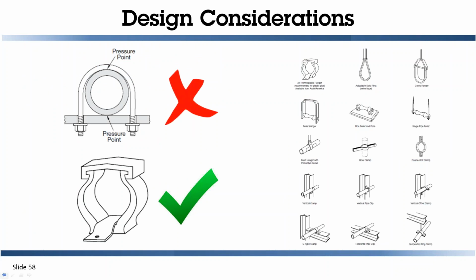When working with plastics, we want to restrain the piping system using a pipe clip designed for plastics. Anything but a U-bolt is preferred. U-bolts put pressure on the top and bottom of the pipe, and they get tightened down until they can't be tightened anymore. You have stress points on the top and bottom of the pipe, which is a failure point in the future. A lot of manufacturers are making metric pipe clamps, which is what our systems use. But any of these on the right-hand side would be perfectly acceptable for plastic piping.